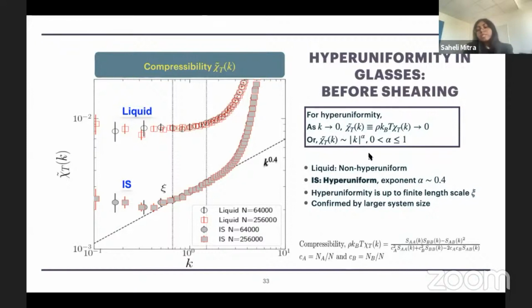Because in fact, this compressibility is a function of partial structure factors. And for a system to be hyperuniform, this compressibility will have a power law dependence in the low wave vector regime. So we can see that clearly there is a difference between liquid and the corresponding inherent structure. In fact, in the low wave vector regime, the liquid is flat, and for the inherent structure, we can fit it to a power law. The exponent of the power law turns out to be 0.4, meaning that the inherent structure is hyperuniform in nature.